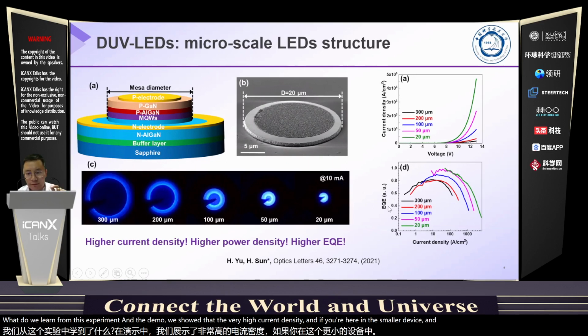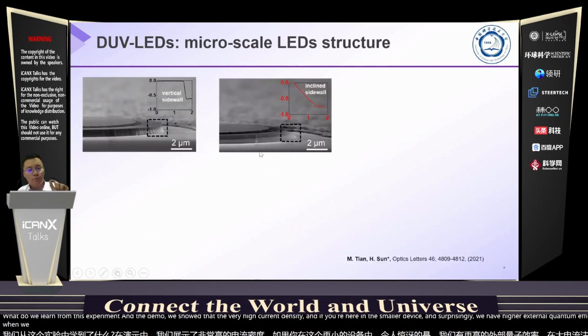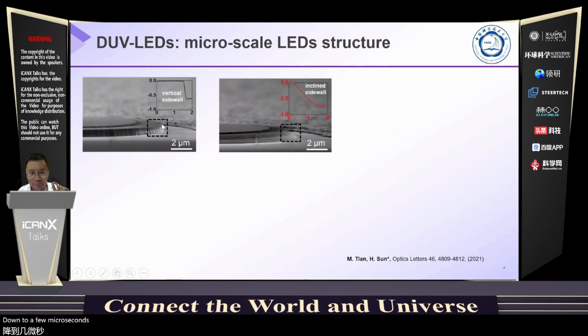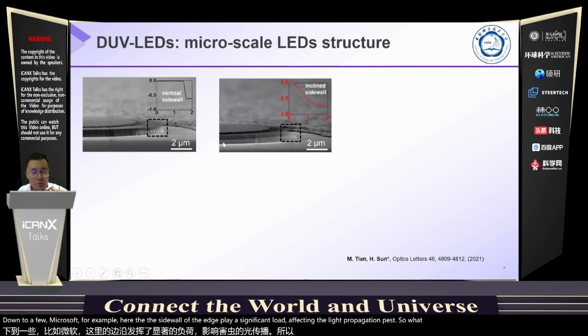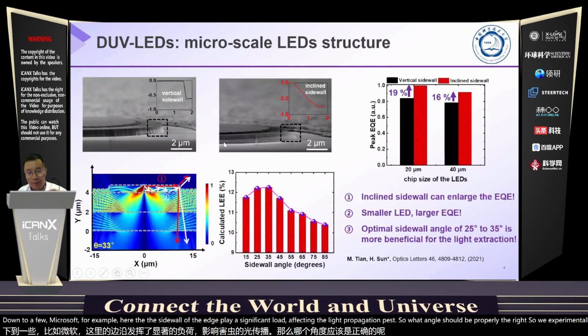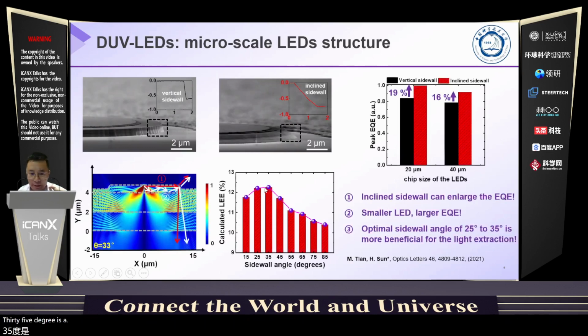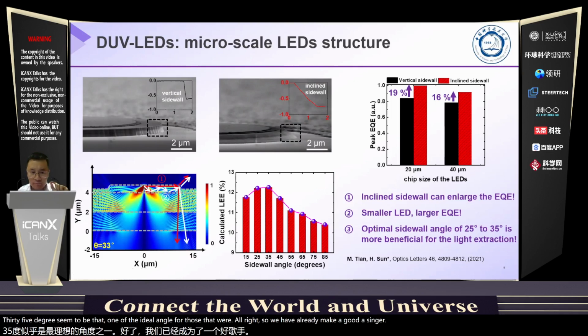And surprisingly, we have higher external quantum efficiency in the large current injection regime for those micro LEDs. But when we shrink the device down to a few microns, for example here, the sidewall or the edge plays a significant role affecting the light propagation path. So what angle should be appropriate, right? We experimentally demonstrated that 35 degrees is the highest. Meanwhile, this is verified by theoretical FDTD simulation that 35 degrees seems to be one of the ideal angles for those sidewalls.